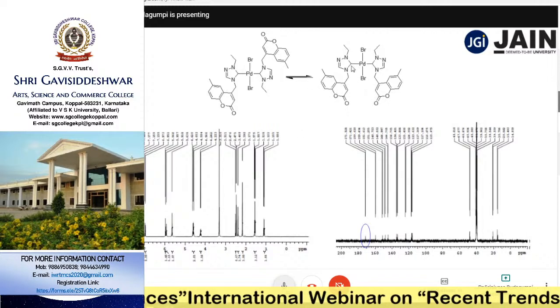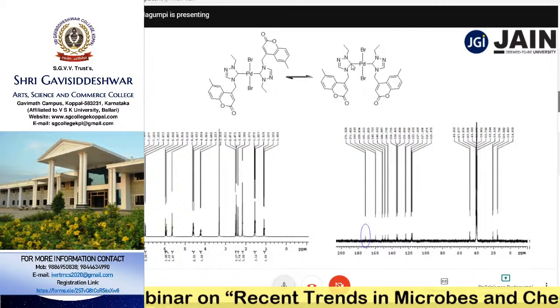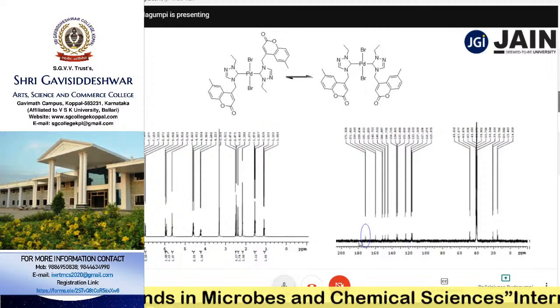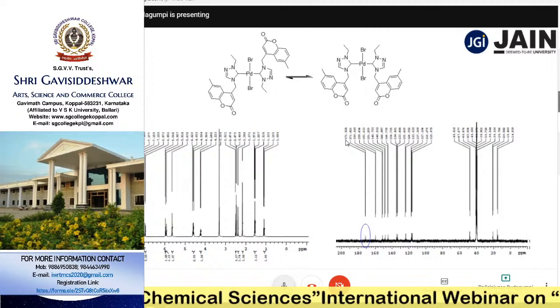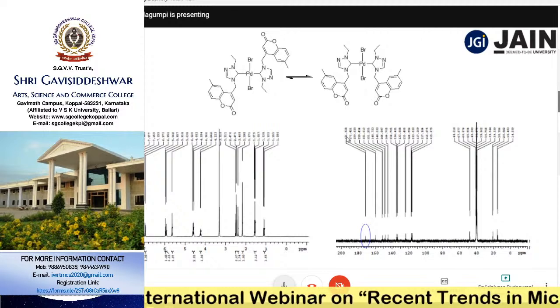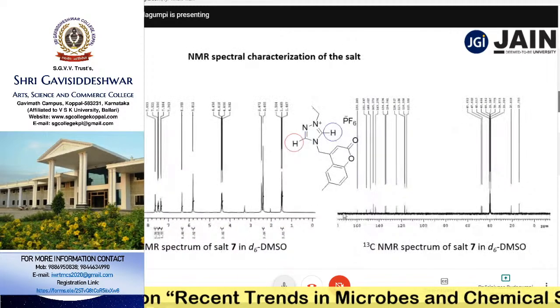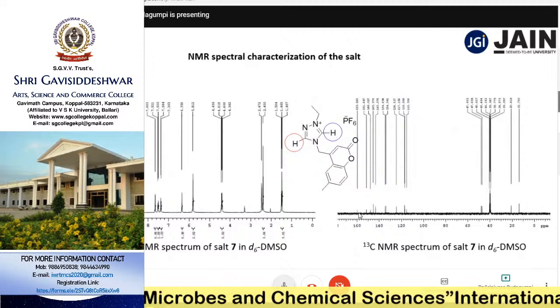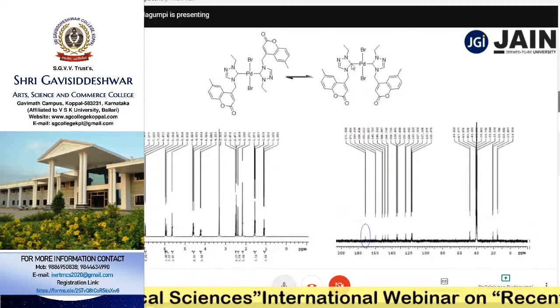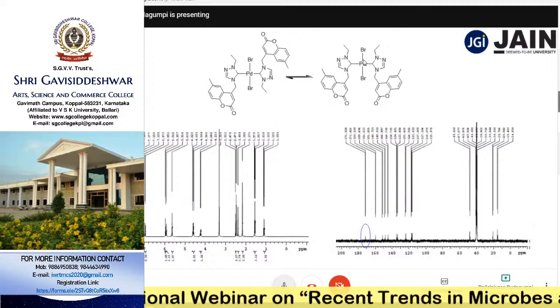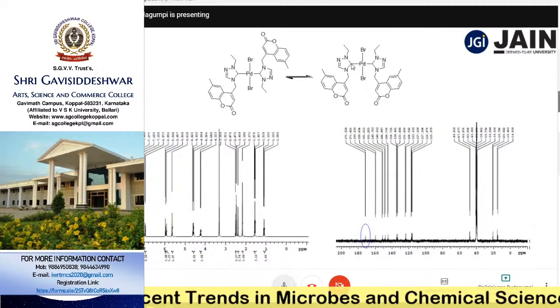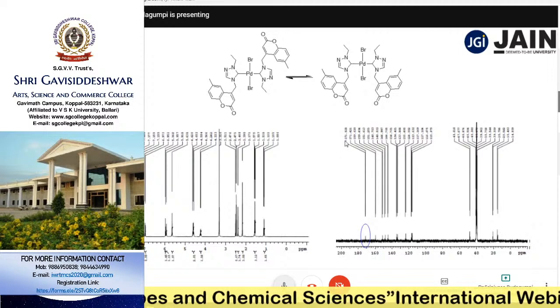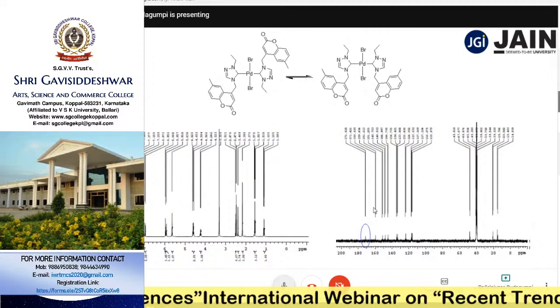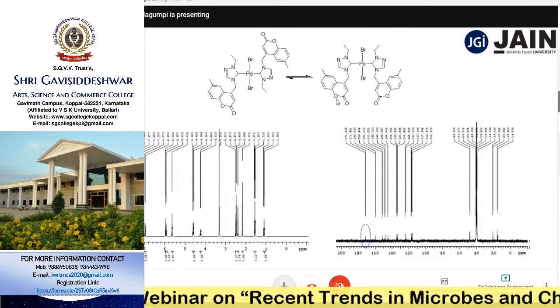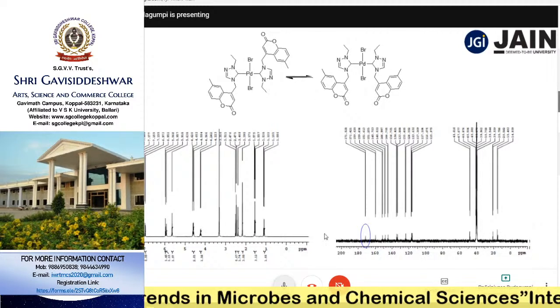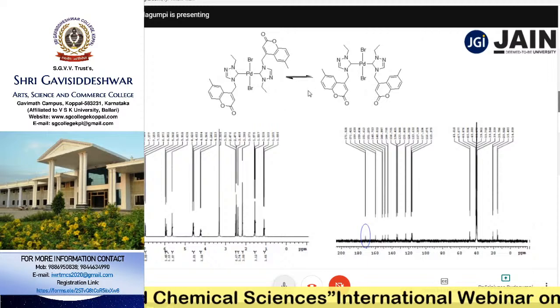Fine. So this particular carbon resonance is 135 in the carbon NMR of this salt, while in the complex case, we could see a resonance appeared at 171. Whereas in the salt, there is no 171 resonance. And this could be attributed to the resonance of the carbene-carbon, which is attached to the metal center. Because of the electropositive palladium center, this carbene-carbon is deshielded and appeared at 171 ppm. These are the two indications that one can easily say the successful synthesis of the palladium complexes. And this particular NMR pattern explains to us that the rotamers are possible in the solution.